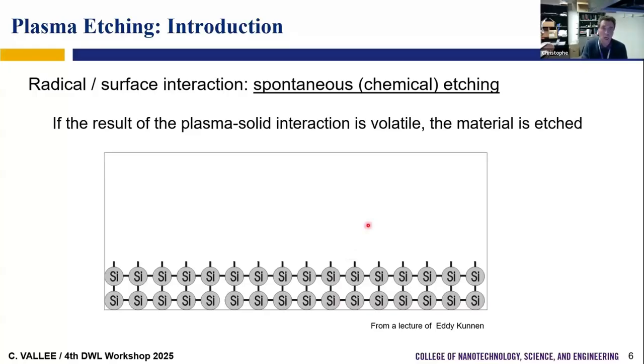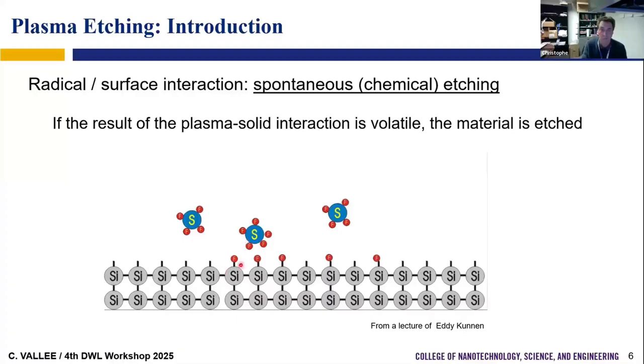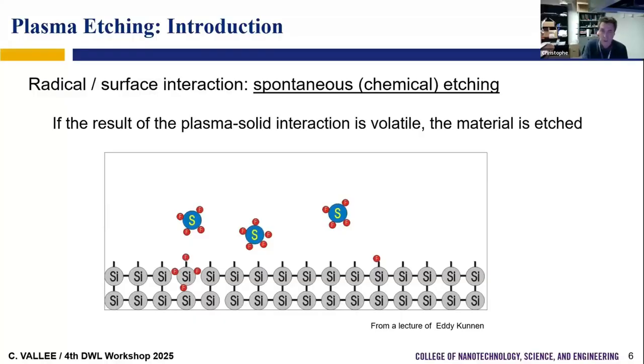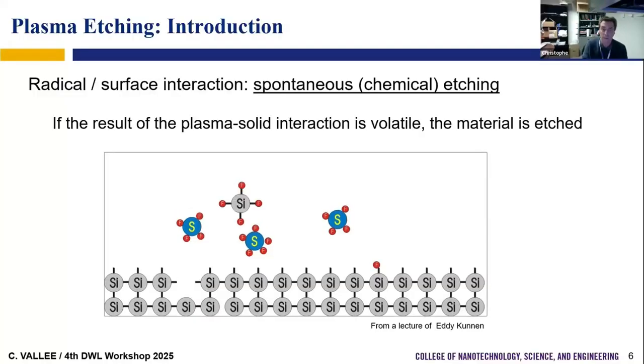We want to have a plasma that interacts with the solid, and we want the final product to be volatile. For example, we use a fluorine-containing gas like SF6, and we use a plasma to take this stable molecule and create radicals, to extract from the molecule some etching agent. Then the fluorine atoms can react with the material, for example silicon, and form silicon-fluorine bonds. When four fluorine atoms are attached to the silicon, SiF4 is not solid, so we have a volatile byproduct, and we are etching the silicon. So this is chemical etching.